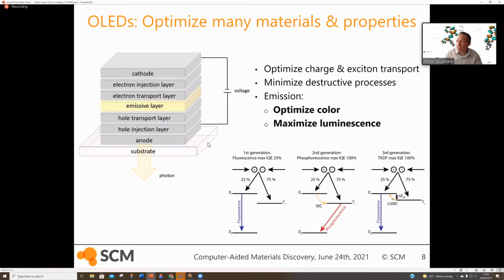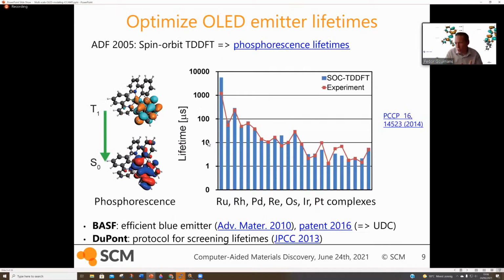And so with this spin-orbit TDDFT, you can actually calculate the lifetime of a T1 state for emitting to the S0 state, or the T2 state or T3 state. But you can calculate the phosphorescent lifetimes of these triplet states. And so that was picked up by our neighbors in Germany, by BASF, who used this to screen materials to try and find an efficient blue emitter. So blue is the most energetic emission, and that's typically also the most difficult color to get right. But they picked up this spin-orbit coupling TDDFT.